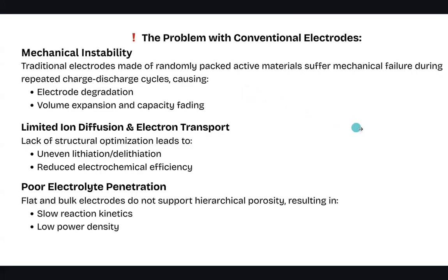Let's see what the problems with conventional electrodes are. The first thing is they are not stable. First is mechanical instability. Traditional electrodes made of randomly packed active materials suffer mechanical failure during repeated charge-discharge cycles. This causes electrode degradation and volume expansion.